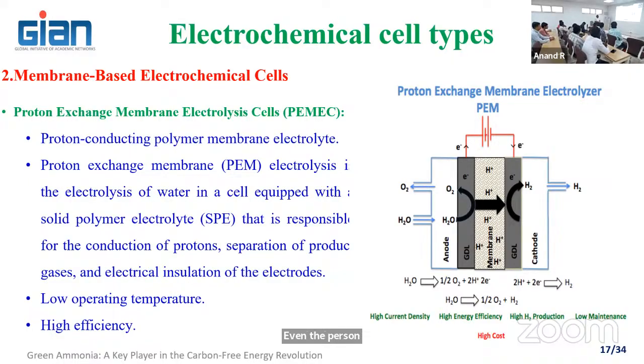Normally, if you operate at ambient temperature, it will not create any issue. But the Nafion membrane is going to be coated on one side with the catalyst support for the anode, and on the other side you are going to support the catalyst for the cathode. So the catalyst coating also plays a major role. When you apply a coating of certain micron or nano thickness, we need to ensure that the catalyst is coated on the thin film. So the life depends on the catalyst material and also on operating temperature and pressure.